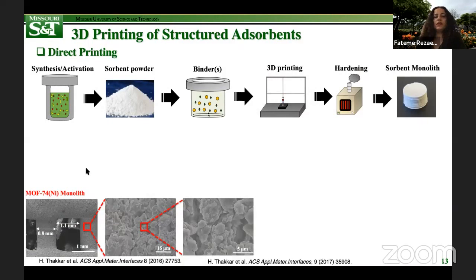This simple schematic describes the direct printing approach, and these SEM images below show the morphology of a MOF monolith made by this method. Here, the adsorbent is first synthesized and activated, then mixed with an appropriate binder and solvent or any other required additive such as plasticizers to form a paste with optimized viscoelastic properties suitable for printing. Then the structure can be digitally designed using AutoCAD software and printed. In the final step, we have solvent removal and activation, which will be conducted after 3D printing.